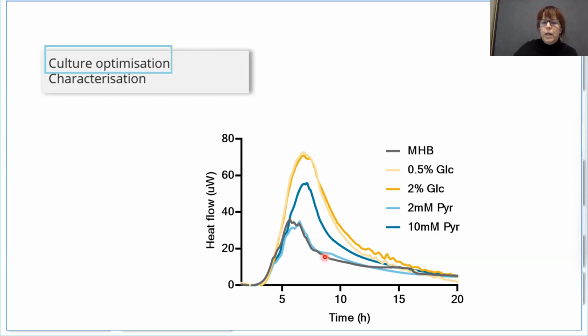The gray one is without this additional carbon. If you add glucose, we can see it doesn't matter which concentration of glucose, but you increase the activity of the microorganism very, very much just by this addition. For the pyruvate addition, we can see the lower concentration doesn't affect the growth or the activity very much, but you need to add more to be able to get that effect on the activity of the bacteria.